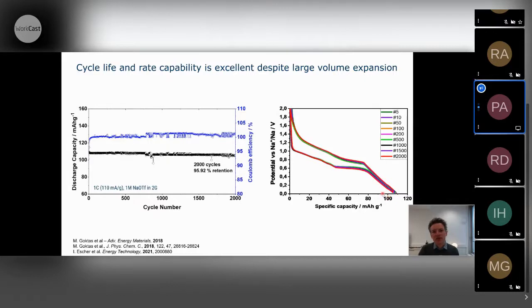So even after 2000 times storing sodium in this material, there's no degradation of the crystal structure, which is, I think, quite remarkable because the solvated ions are very large. So the breathing of this graphite is actually quite strong.